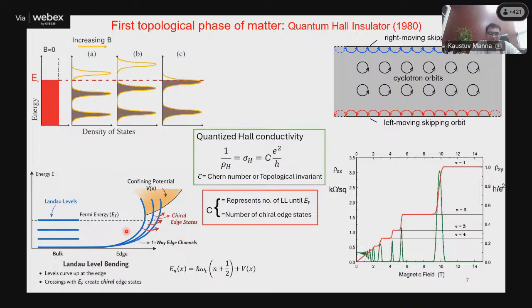As a consequence, if you plot the dispersion with respect to energy, you see that the Landau level inside the material is flat. As it goes towards the edge, because the outside potential is infinite, these levels have to bend. Because of the bending of this edge state, you see here at the edge, the Landau level crosses the Fermi energy. As a consequence, if you have 3 Landau levels below the Fermi energy, you have 3 edge states, because now 3 Landau levels are crossing this Fermi energy at the edge of the material. So you get C equal to 3 in this case.